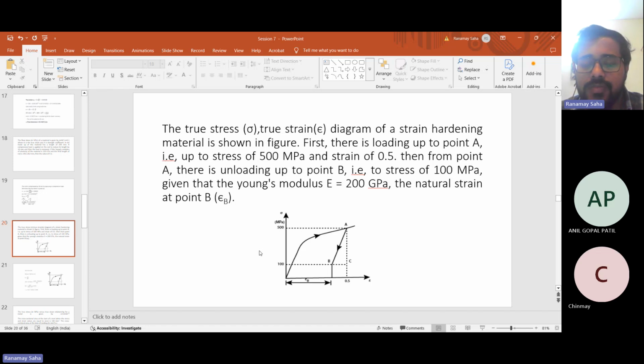Again, you know from Hooke's law that Young's modulus is the slope of a stress-strain curve. So just equating E as AC upon BC, you know AC as the difference between the stress at C and stress at A, and BC remains the unknown. If you can find BC using that, then you can simply subtract it from the total strain value up to point A to find the strain value at point B. So BC becomes 400 upon 200,000, which is equal to 0.002, and you subtract this from the total strain value, 0.5, to find the strain value at point B. Please take a note and then we'll proceed to our next question.